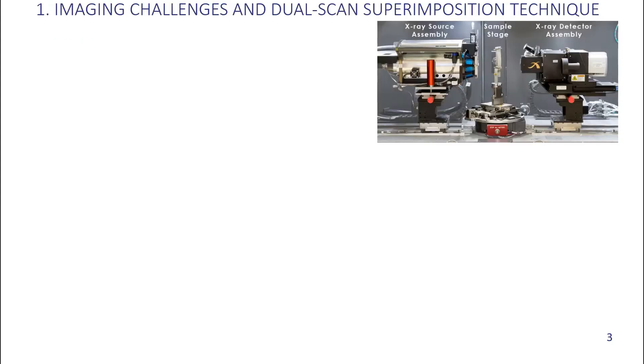For those who are not very familiar with X-ray CT, this image shows the typical setup. It consists of an X-ray source, sample stage, and detector. Around 2000 projections are acquired while the sample is being rotated over 360 degrees. These projections are then reconstructed to give the 3D electrode microstructure.